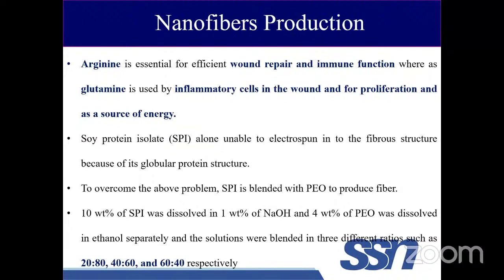When we did electrospinning for these ratios, 60-40 doesn't give us nanofibers because of its higher proportion of soya protein isolate. Only 20-80 and 40-60 gave us nanofibers, right? Out of these two samples, we took 40-60 for the further studies because 40% soya protein is higher than 20%, and is going to give us a better yield than 20%. So we took 40-60 and then did electrospinning.